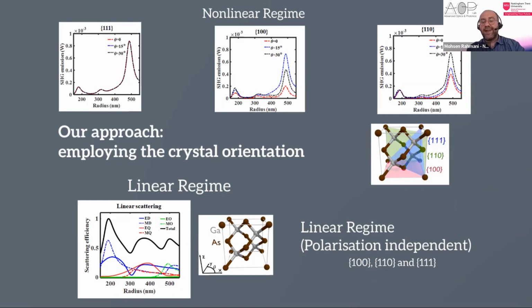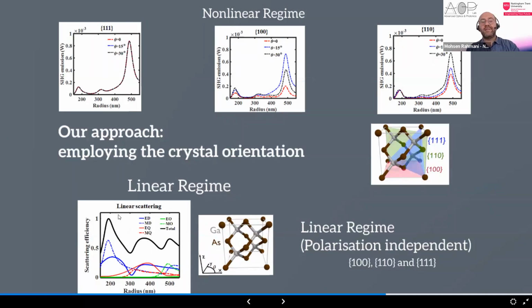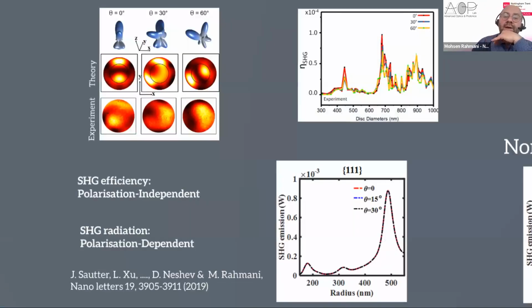So I want to remind that in the linear regime, because it's just based on the refractive index of the nanoparticles, you don't see any changes in the linear properties if you use different orientations here. For all different cases, the linear scattering is exactly like this, identical. But when you go to the nonlinear regime, you see that the crystalline orientations are significantly different. For example, for 111, at different polarizations of the input light, you can get the nonlinear signal in different directions and closer to the normal. Here in this case, you see that closer to normal, you can get some signal.